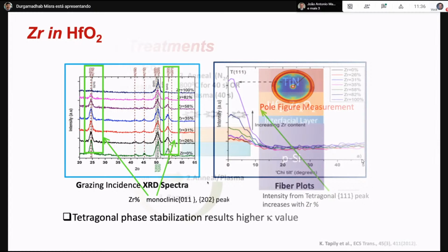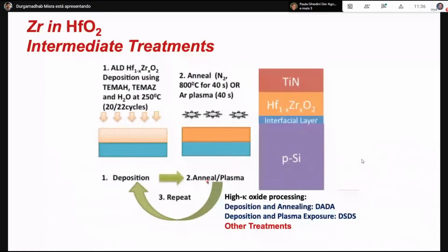But once we start this, the other thing I mentioned, because of the ALD processing, we can actually do several interesting things around it. Like, for example, if you deposit few cycles and then anneal the sample, and then deposit few more cycle. Even before you complete 3 nanometer of dielectric, you can have several deposition and anneal, deposition and anneal. That way you can densify the film and improve the characteristics of the dielectric. So also there is another process started, deposition and plasma exposure. What plasma exposure does, if you give very low energy electron exposure to the surface, it actually reduces the number of oxygen vacancies and increases the quality of the dielectric. And so that is called DSDS. We call deposition annealing as DADA and deposition and plasma exposure as DSDS. So many other treatments you can do during this time.